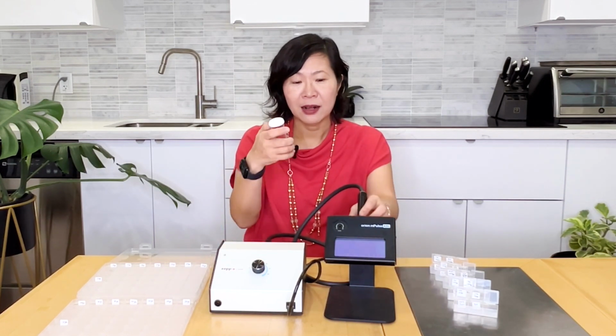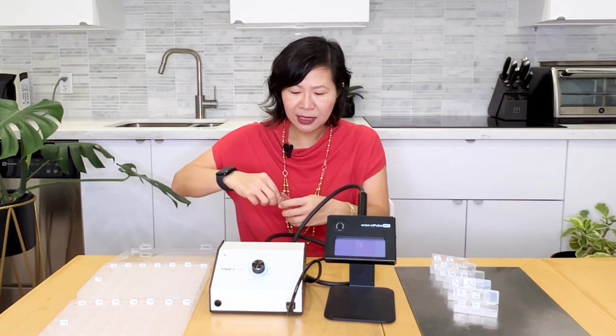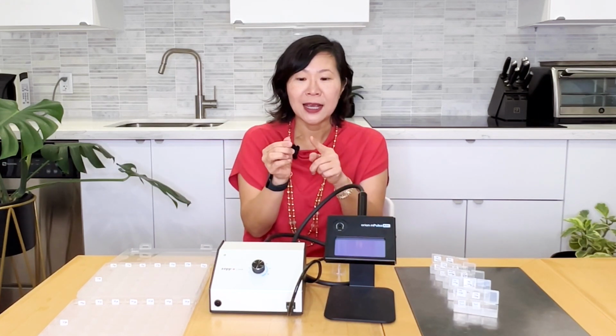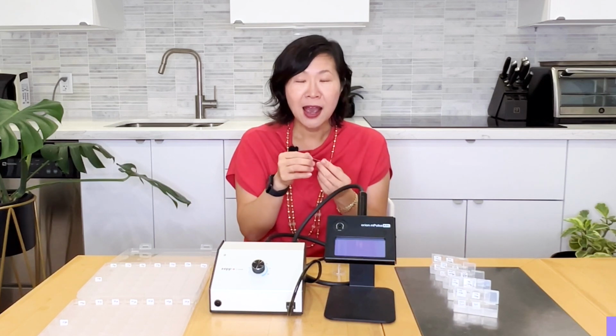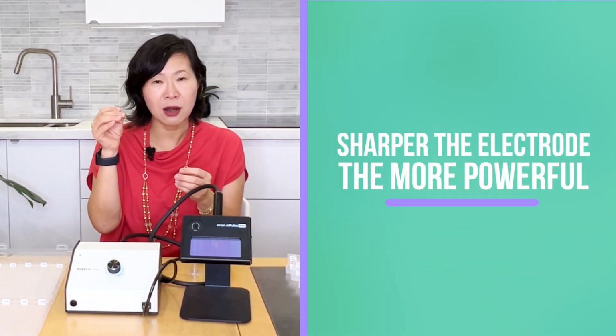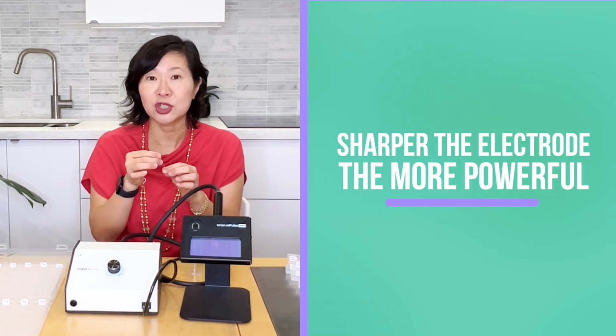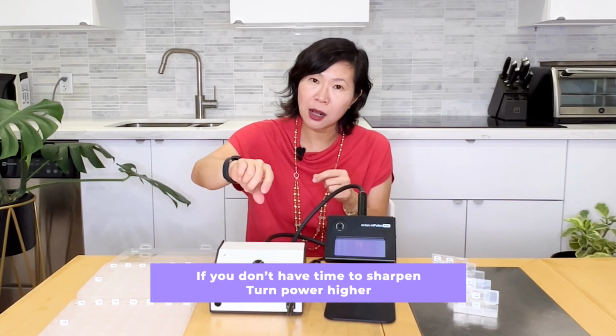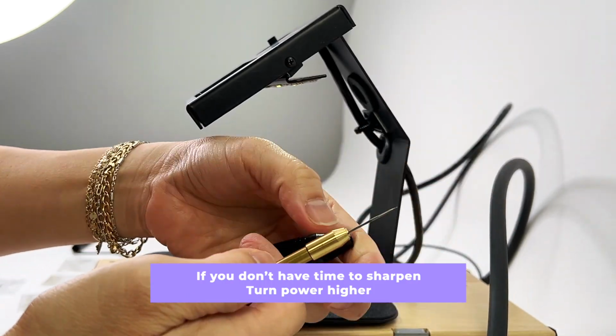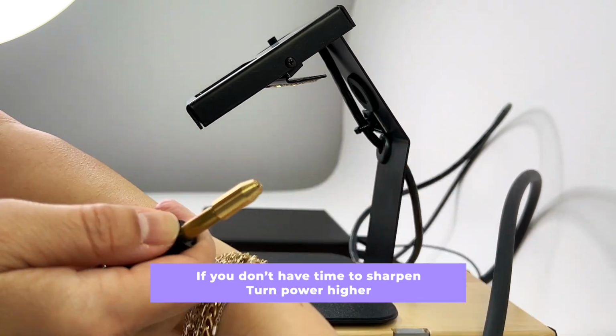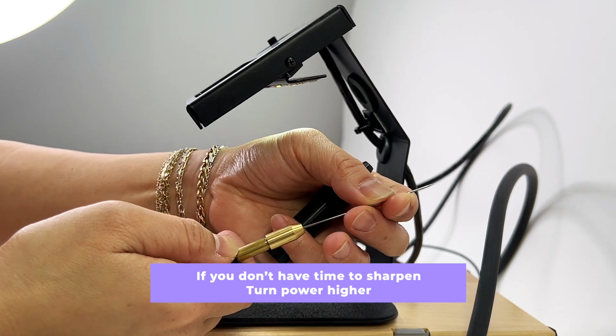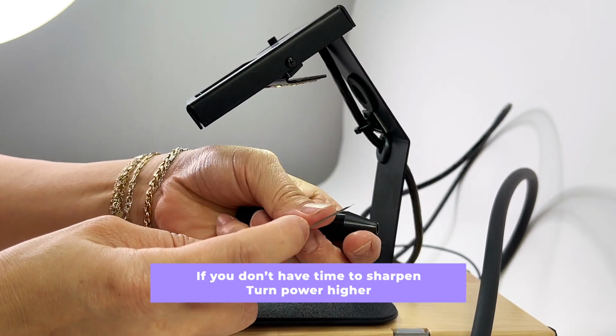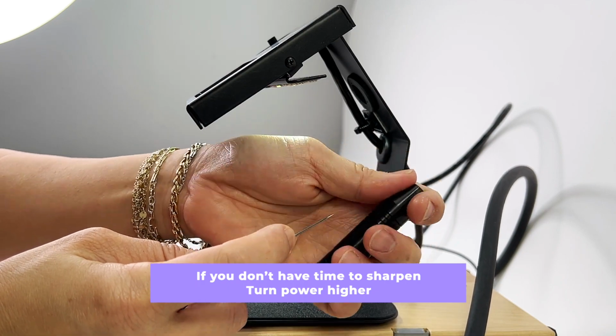Another factor that impacts how powerful the weld is, and therefore the power setting, is the electrode. With tungsten electrodes, basically the sharper it is, the more powerful it is. And you will find that if you are welding for a long time without sharpening, it becomes a little bit weaker and you have to turn the power setting a little bit higher. So the sharper it is, the more powerful; the duller it is, the less powerful, and therefore you have to increase it. That is the rule of thumb.